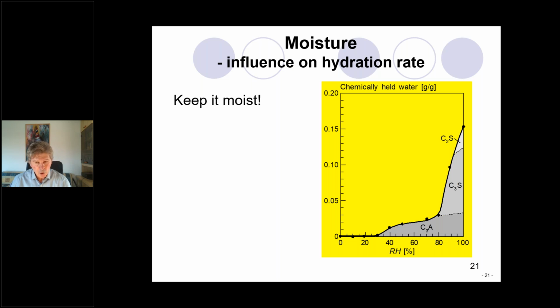And then most of my presentation is devoted to moisture. We know well that we need to keep concrete moist. Keep it moist. This is a rule. You see, the different phases I spoke about before, C3A, C3S mainly, and C2S, need a relative humidity high enough to hydrate. And in a very dry climate, in a very low relative humidity range, we can neglect the formation of the hydrates because there is no chemically held water, nothing.